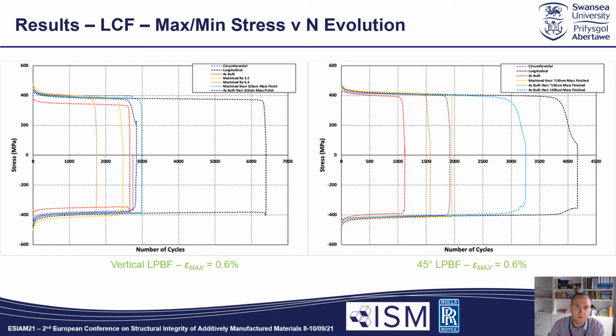Looking at the fatigue results in a little more depth, what we have here are 2 separate plots showing the evolution of maximum and minimum stress across the 2 build orientations, with the verticals to the left and the 45s to the right. In each case, plotted here are the specimens of each of the different surface finishes which were subject to the same maximum strain value, which is 0.6%. The graphs show that in all cases, there is a small, almost minute degree of hardening in the first couple of cycles, which is actually quite difficult to see, which quickly succumbs to a period of cyclic softening, which takes place over 100 cycles or so, after which the stress flattens off quite nicely to a very stabilized condition. In both cases, the as-built specimen exhibited the smallest stabilized stress range.